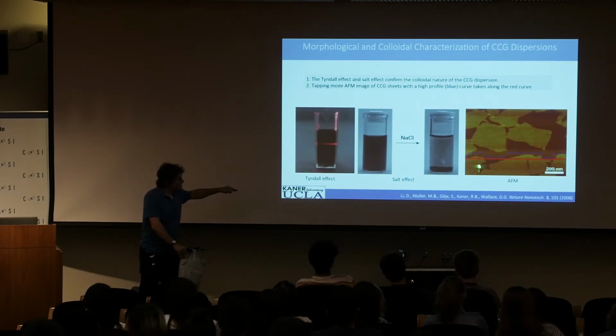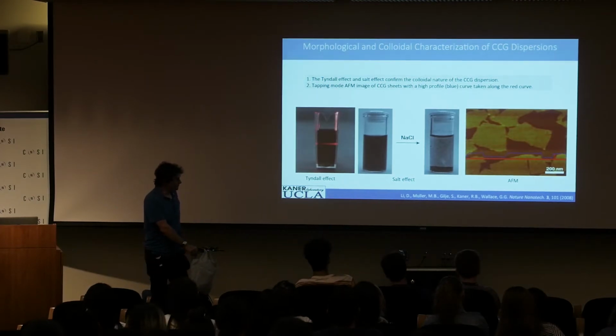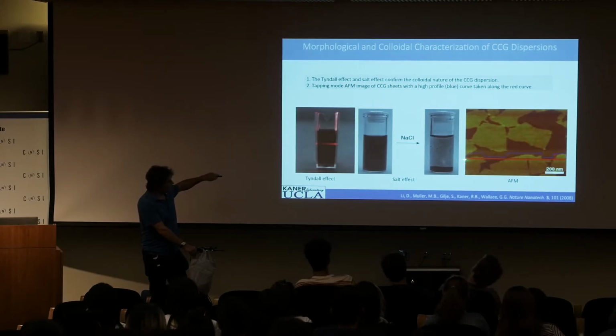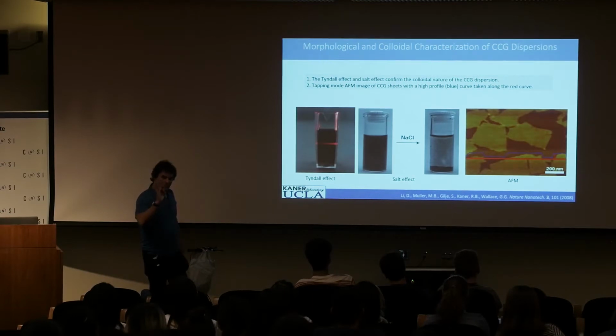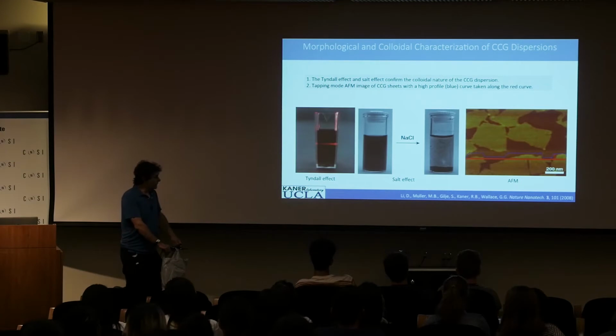And this is an atomic force microscope picture. And this is the graphene we made. You see all these flakes. And if we run a probe along it, they're about 1 nanometer in height. They're very thin. So people have decided these are individual layered flakes.